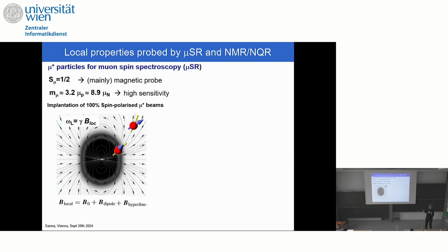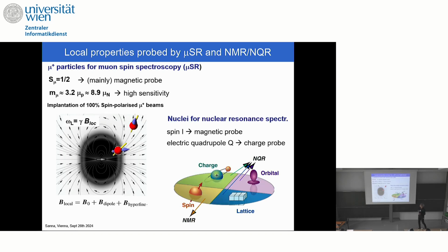In particular, I would like to remind that the muon has a 1/2 spin, which means that it is mainly coupled to magnetic degrees of freedom. Not only, but for our purposes today, it is mainly coupled to magnetic degrees of freedom. It has a big magnetic moment, almost 10 times the nuclear one, so it is highly sensitive. And in a standard dipolar interaction, we can think about the muon spin precession around a local field at the muon site. We are able to detect these precessions through the oscillation typically in a muon signal, and we can detect the contributions to the local field.